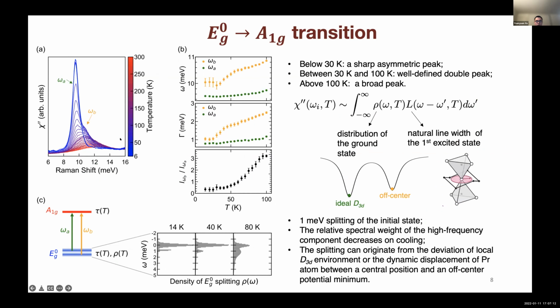And above 100 Kelvin, we can only see a very broad band. The Raman intensity can be understood by the convolution of the density of states of the ground state and a Lorentzian function, which is determined by the natural line width of the singlet. And we obtain the density of states of the ground state by using a deconvolution procedure with an empirical Lorentzian function. The result shows a pronounced two-component distribution between 40 and 100 Kelvin.